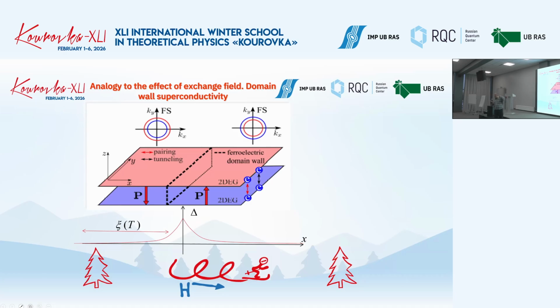You see, there is some boundary along this y direction which separates the domains with different orientation of this dipole moment. And we assume that the change in the dipole moment orientation is the cause of the change in the sign of the shift of the bands. And it's quite clear that even if superconductivity is forbidden in the domains far from the walls, it can still exist near the domain walls.